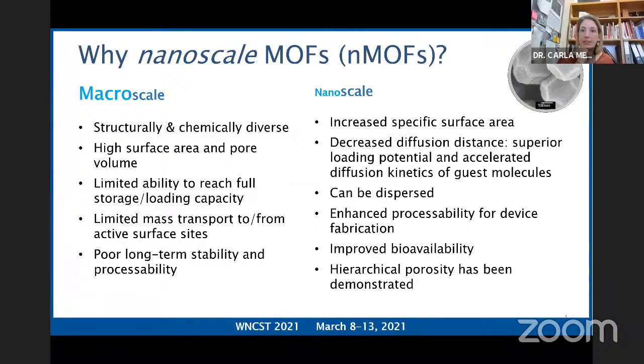They have increased specific surface area. They have a decreased diffusion distance. So now the majority of the pores are located at the surface, decreasing that diffusion distance of guest molecules. So that can lead to superior loading potential, some accelerated diffusion kinetics of guest molecules. We've seen many examples of nanoscale MOFs that are dispersible in a variety of solvents. This also increases their processability. They have improved bioavailability. They have a size small enough to be a physical size that enables intracellular delivery, for instance. And hierarchical porosity has been demonstrated, as well as a variety of other properties that differ from those in the bulk scale.